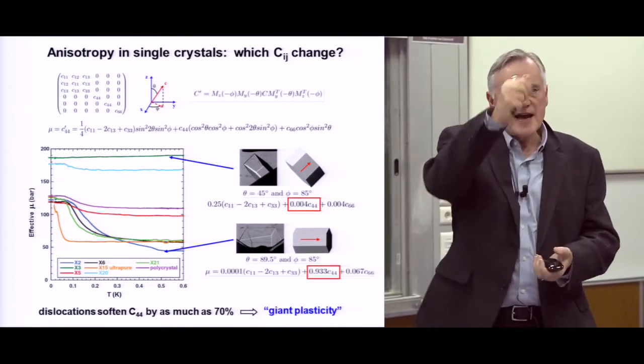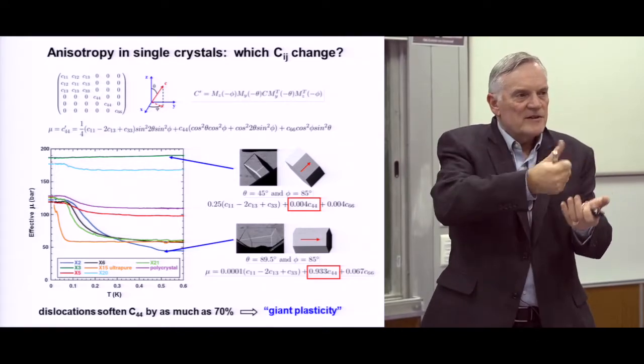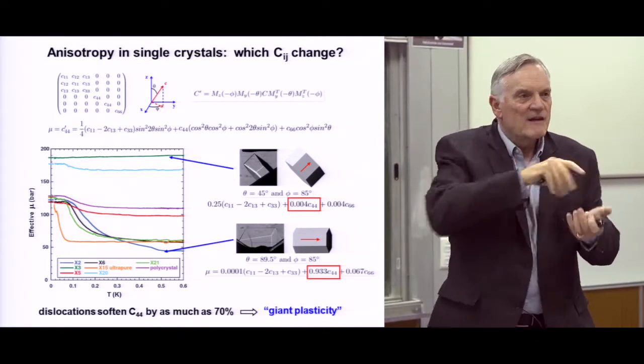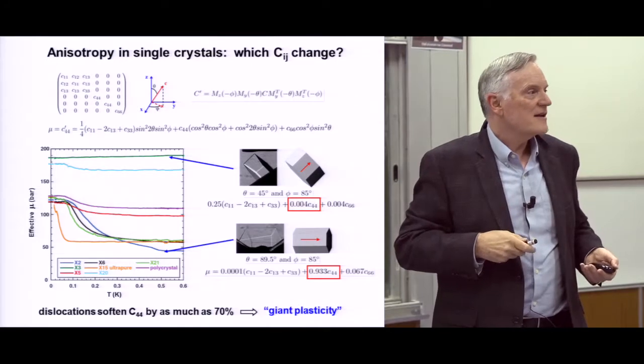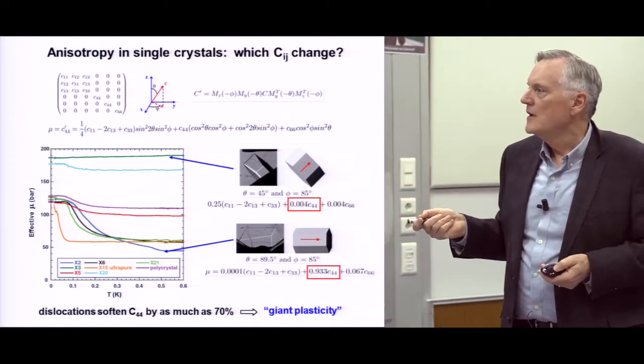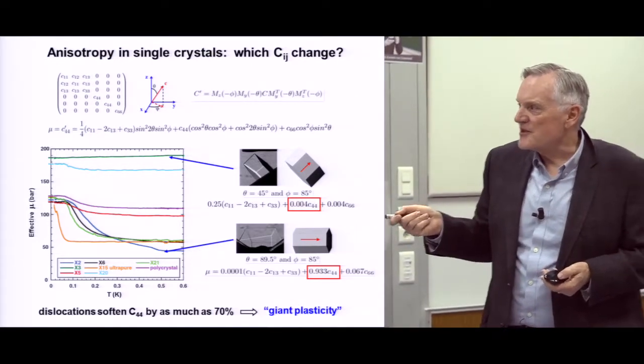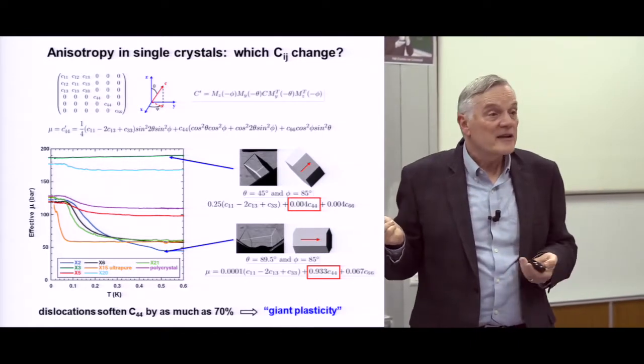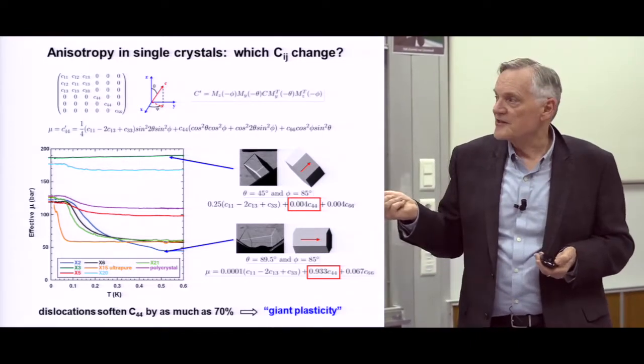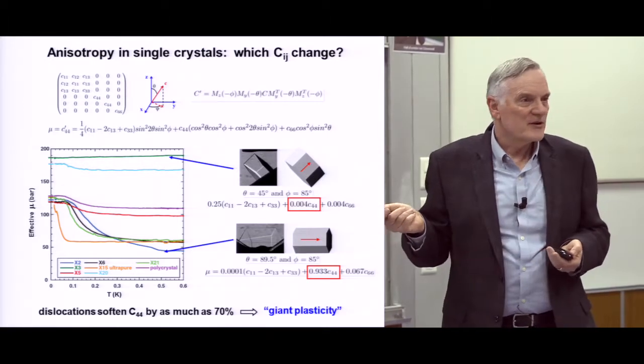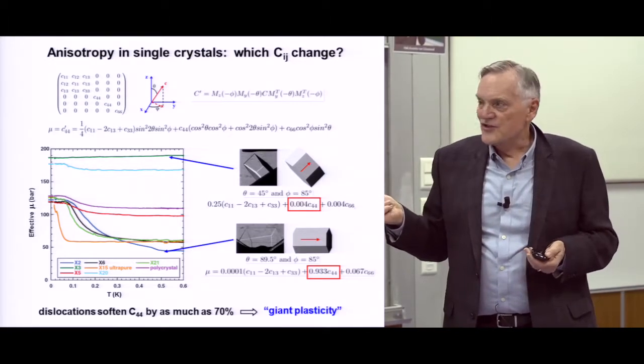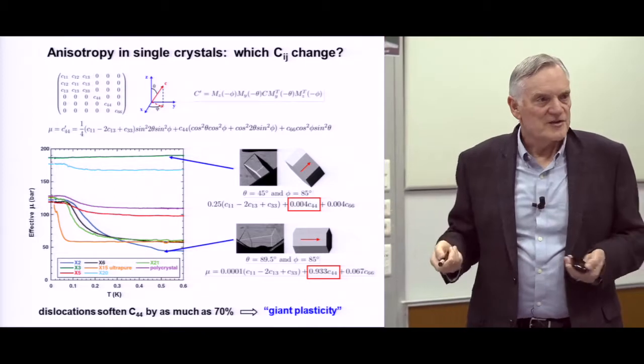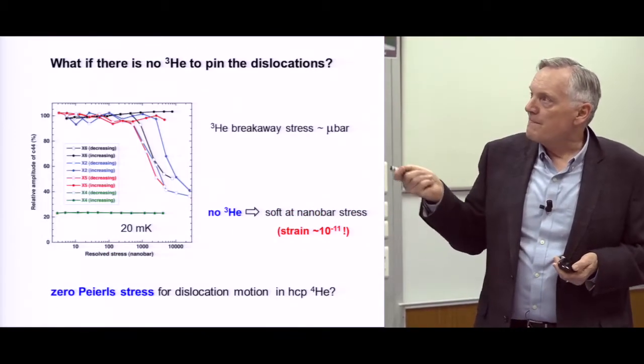That's the plane where if you have a C-axis, you have all these planes stacked with your C-axis this way. If you slide it this way, that's the direction things can slide easily, C44. And so this change is huge, as much as 70% or another experiment, maybe 90%. You lose most of your shear modulus, which is sort of unheard of in regular materials. So that was, we referred to that as giant plasticity because it's dislocations moving and softening it.